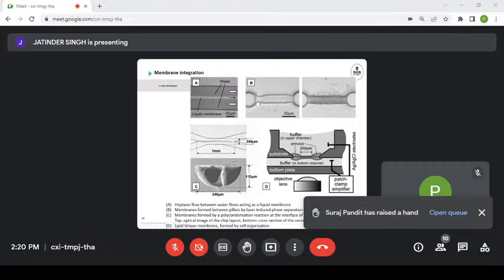Here we've got a polycondensation reaction. We've got a couple of chemists in the room. A lot of us will have worked on the synthesis of nylon, where we've got a two-phase reagent system and the polymer forms where the two reagents are in contact. You can use that in microfluidics. You can flow your two reagents alongside each other. The reaction takes place at the interface. Exactly what the people have done in this paper here. So we had reagent A, reagent B, and the polymerization reaction happened at the interface, just like when you're making nylon. And here you can see an SEM where we have a membrane that's formed in our microchannel.